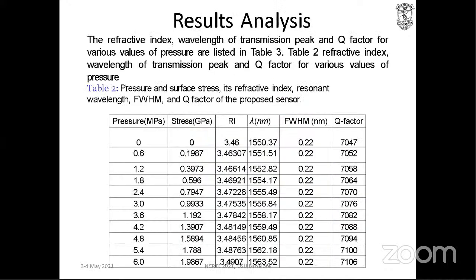So these are the result analysis. You can see the quality factor is 7047. It's a good quality factor because Q should be very high for getting good sensitivity. For 0, the Q factor is 7047 and the wavelength is 1550.37 nanometer. If you apply 0.6 megapascal, the stress is 0.1987, and the wavelength changes to 1551.51 nanometer.